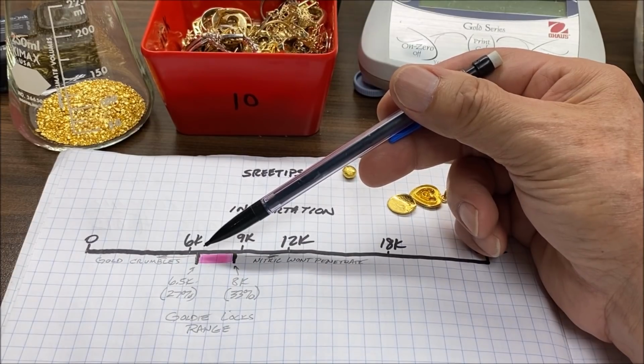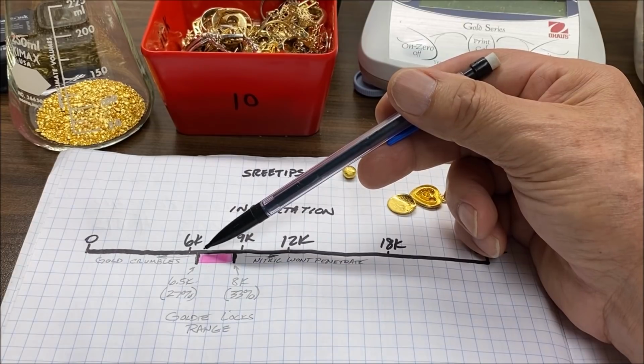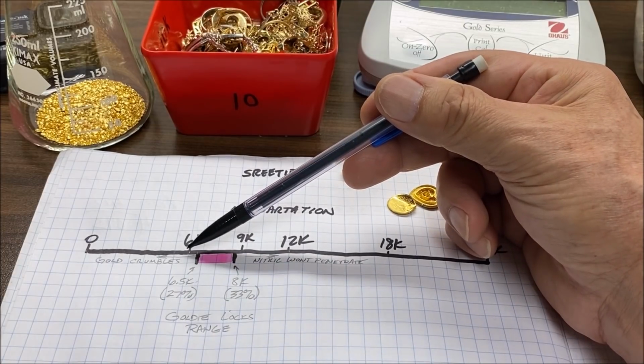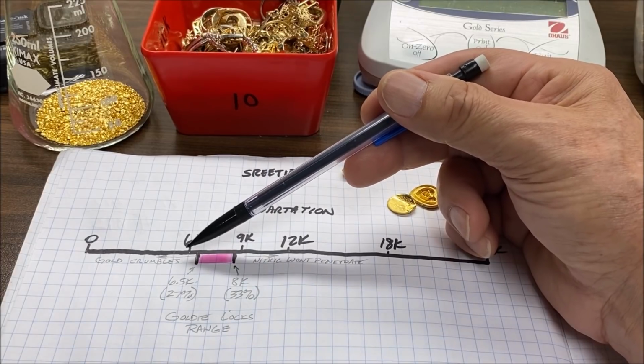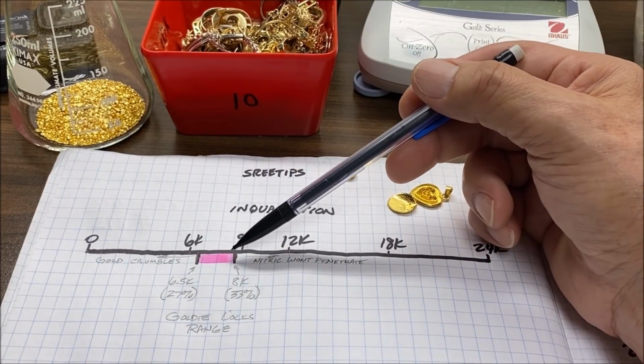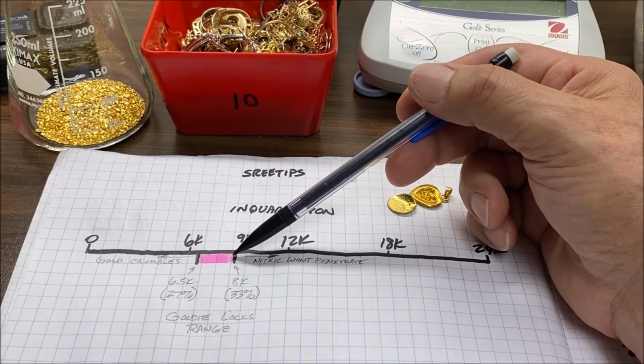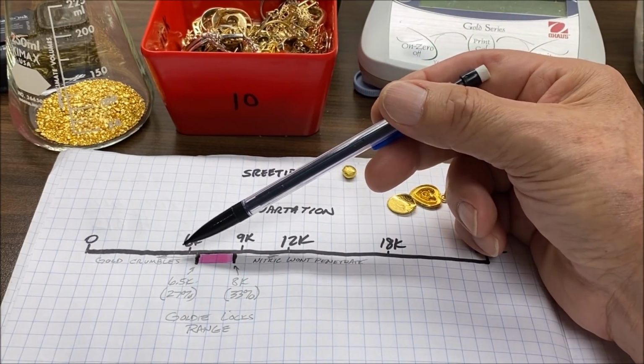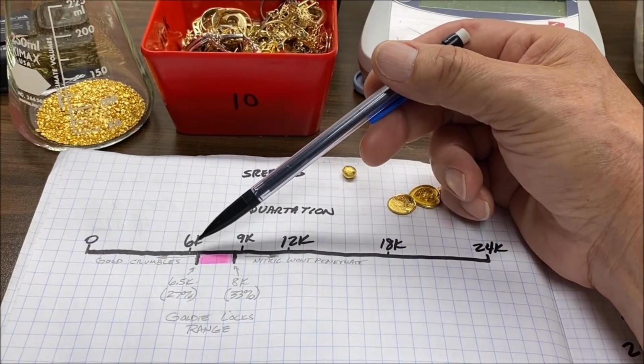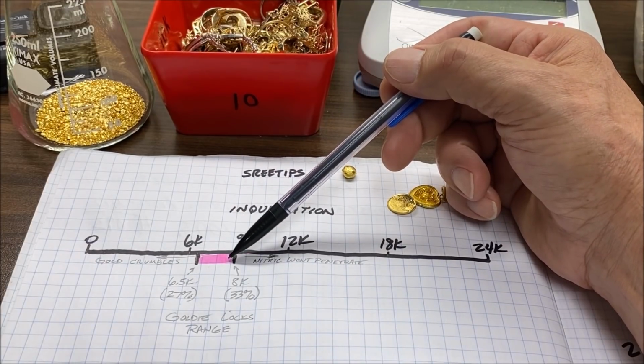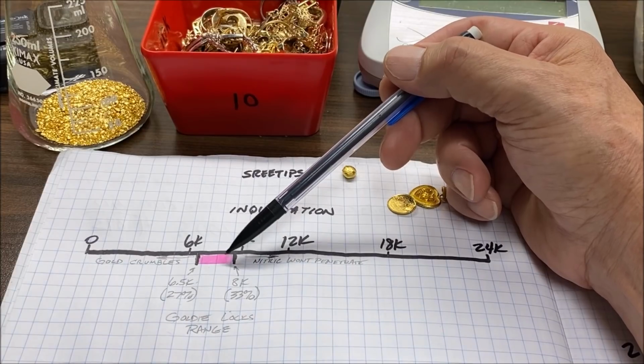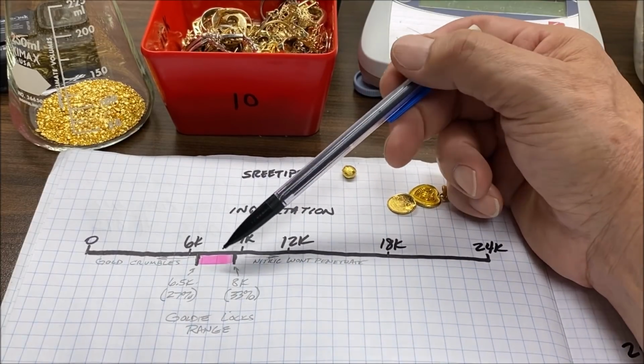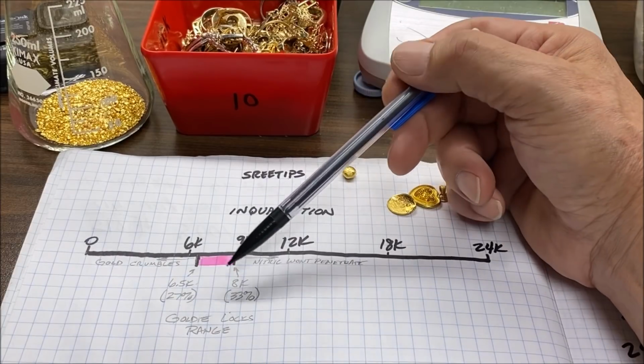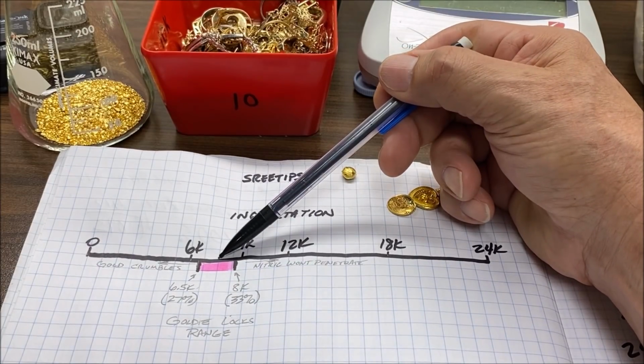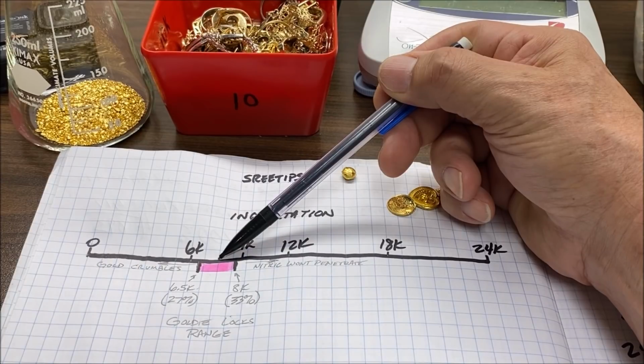So the lower we get close to this 6.5K range, the quicker the nitric acid will remove the base metals and silver from our inquarted gold. But the closer we are to having our gold fall apart and crumble into a powder and make separation difficult. The higher we get in this range, the less likely the gold will crumble, but it will take longer under the nitric acid boils. So if we stay in this range right here, 6.5K to 8K, then we will get the best results when we boil the inquarted gold in nitric acid.